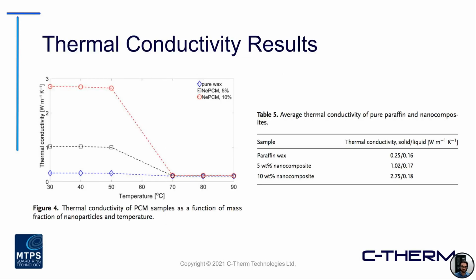So just looking at some of the results that were obtained here, we can see from the graph on the left, or table on the right, compared to the pure wax, so the pure PCM that was used, fairly low thermal conductivity as was expected across the full temperature range. But you notice that by increasing the additive or the filler material here, you're noting a fairly significant increase in thermal conductivity going from 5 to 10% loading.